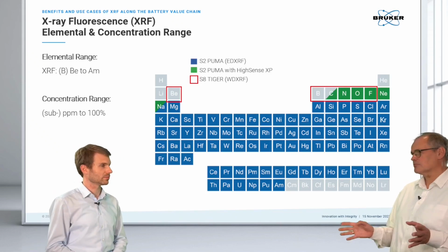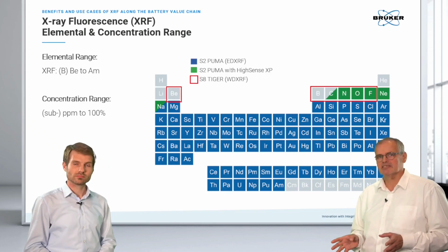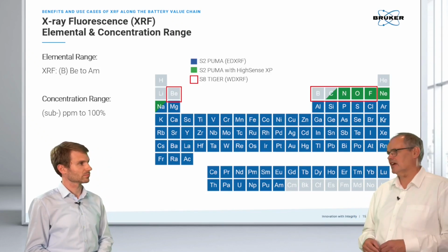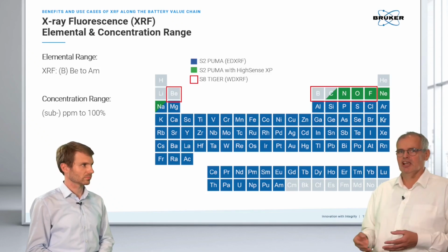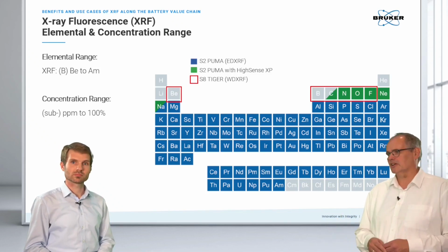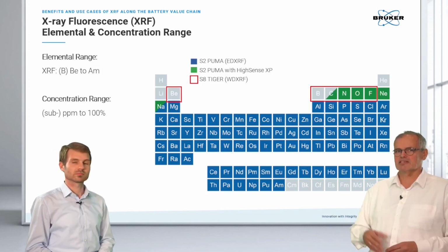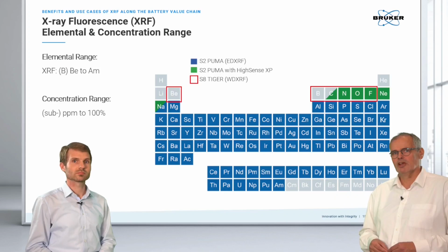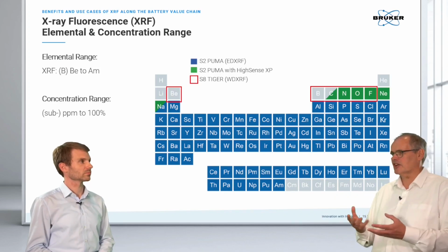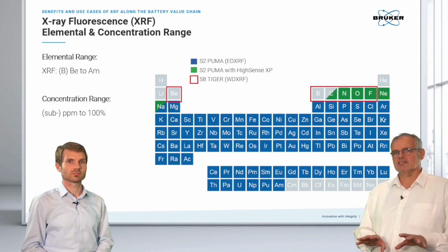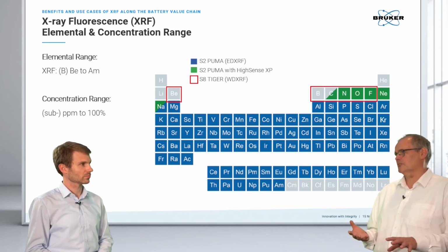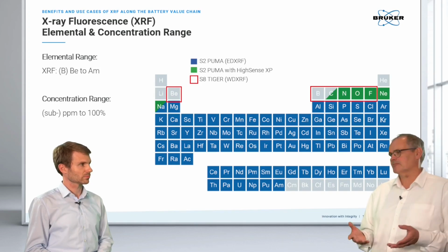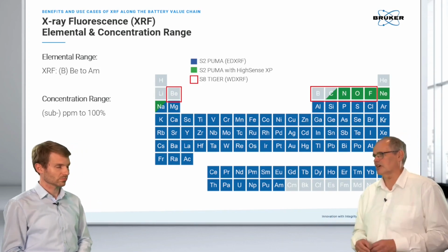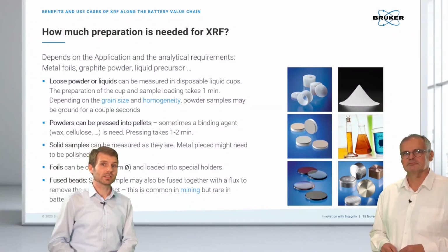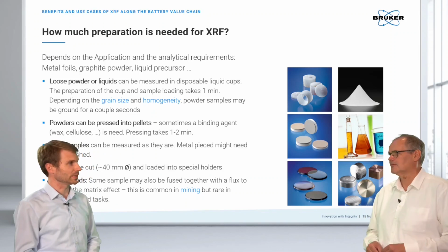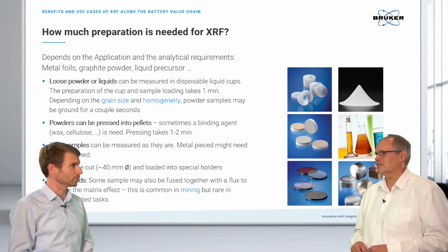Yeah. There are some gray elements we cannot analyze directly, but there are ways even to see and to evaluate those non-measurable elements. For example, the rest to 100, or the Compton ratio. This is the scattered radiation coming from the X-ray tube, which tells us about the general sample composition. So we can access also non-measurable elements, or by stoichiometric ratio. So therefore it also helps to work for lithium or oxygen, right? So maybe Kai, you can tell us a bit more about what type of samples we can analyze in XRF, and maybe also a few words on sample preparation.